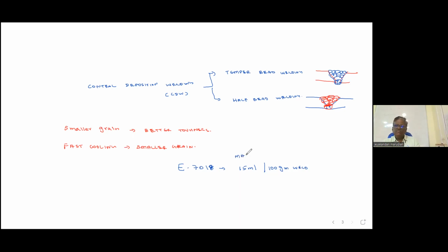So that is the maximum hydrogen allowed. This electrode should not be used for temper bead and half bead welding. You should not use this. We have to use either E7018-H8 or H4 only. Only these two are allowed. H8 is another 8 ml, still low hydrogen. When you are using H8, post heating is mandatory. Post heating at 500 degrees Fahrenheit is required. If you are using H4, it is not required, because it is very low hydrogen. Post heating is not required.